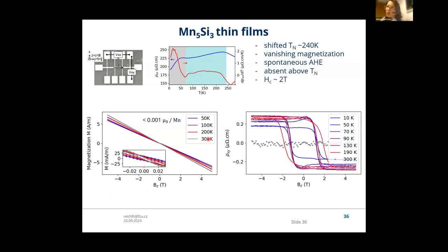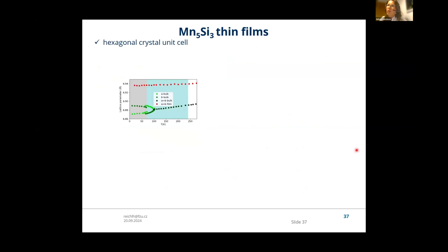This is in clear contrast to the transport data. Here I'm showing the anomalous Hall effect as a function of the out-of-plane magnetic field. And we see that in the full temperature range where the sample is magnetically ordered, we observe a robust anomalous Hall effect, which is spontaneous, present in zero magnetic field, and the effect disappears above this 240 Kelvin, and at room temperature where it's paramagnetic. So this was work done already some time ago.